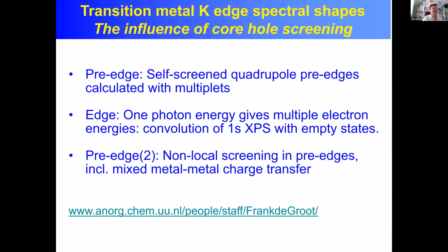If you're relatively close to octahedral symmetry, and that depends on what you call relatively close, but titanium oxide, chromium oxide, ilmenite, they are all relatively close. They are distorted octahedra, so that means that the dipole-quadrupole mixing is not large.